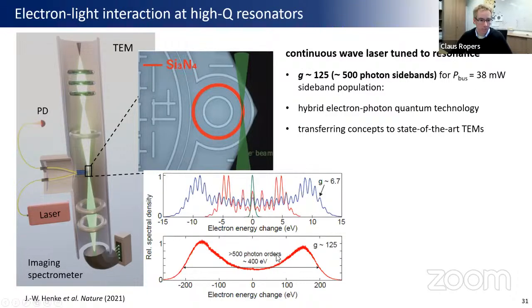Yeah. And the coupling here is actually so strong that all of these experiments do no longer require the ultrafast, let's say femtosecond laser excitation, but can be done with low power continuous wave beams, and also can be done in the conventional continuous electron beam. So either using continuous wave laser excitation of the tip or using the standard continuous electron beam. So we can populate multiple of these orders, actually going to hundreds of photon exchanges, which means that a single electron either absorbs or emits hundreds of photons. So it's a highly nonlinear process in the electron-light interaction here.